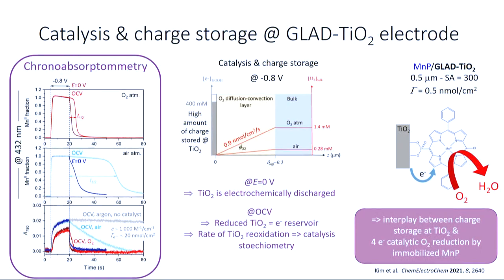Okay? And after this reduction step, what we do is we apply either a 0-volt potential. And when we apply a 0-volt potential, this leads to a very fast electrochemical discharge of titanium dioxide. Okay? And what we notice under these conditions is that we have then a reoxidation of the manganese 2 catalyst by the incoming flux of dioxygen, okay, which is what we expect. And if we leave the system under open circuit voltage, what's happening now is that we have a significant delay, as we can notice here, in the reoxidation of the manganese catalyst by the incoming flux of dioxygen.